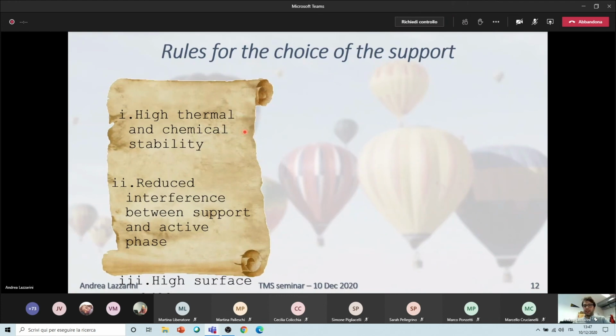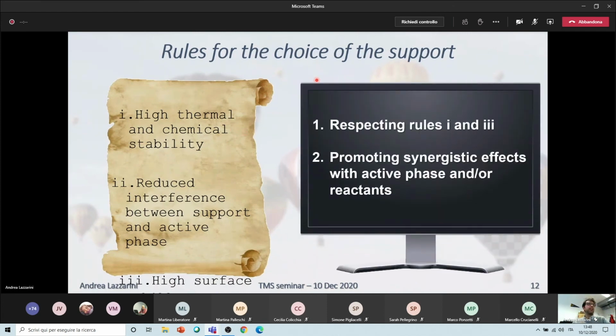Of course, these are the classical rules. I like to name new rules for modern supported catalysts that can be represented in these two points. Of course, the first point respects rules 1 and 3, because you still have to maintain the thermal and chemical stability of the system in the reaction environment, and still guarantee a high surface area value to maintain good contact between the active phase of the catalyst and the reaction environment. But supports can also be chosen in a way that they promote synergistic effects with the active phase or the reactants in order to enhance the activity of the reaction itself.